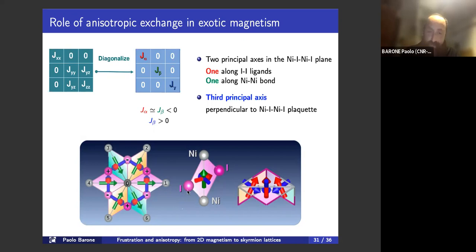The point is that these plaquettes are not coplanar to the lattice layer. You can see it both from the top view here, where this plus and minus correspond to iodine atoms above or below the lattice layer, or from this side view. So these principal axes are canted; they are all pointing in different directions. So this is similar to the anisotropy frustration that I showed you before for the single ion anisotropy, but of course on the two-site anisotropy term.